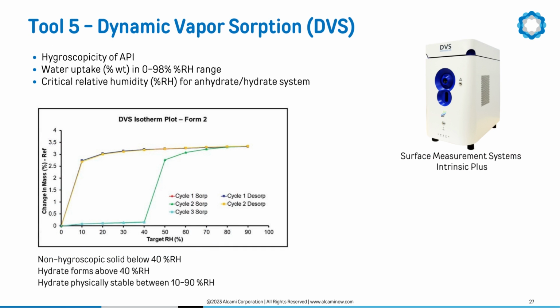Dynamic vapor sorption, or DVS, is another important technique used to assess hygroscopicity of the API. Powders are exposed to relative humidity levels between 0 and 98%, and the change in mass within a given time frame is measured. If API is highly hygroscopic, it will pick up lots of water and become sticky and eventually turn into a liquid. More stable solids may remain free-flowing powders during the analysis. However, as shown in this example, solids may pick up water only above critical RH level, above which they can turn into a hydrate. Hydrate then can be physically stable across wider RH ranges.